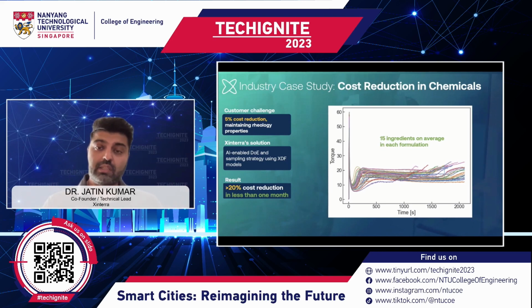That was their target. To them, anything up to 10% was fantastic, and anything beyond 10% cost reduction was unimaginable. And so again, what we did was we took those 15 ingredients that they had, reformulated it with the AI, and suggested new experiments that they could run. Eventually we found we were able to reduce their cost while keeping the performance the same by 23%. So this was mind-boggling for them.